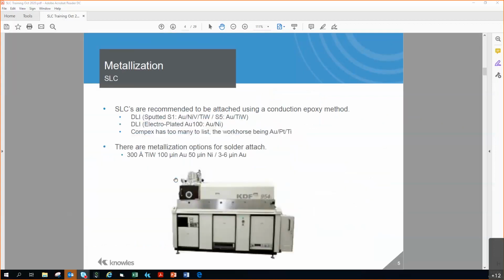All right. So a single layer capacitor is a single piece construction, but there is metallization on each side. We do 2 types of metallization. We use sputtering and we do wet plating. Typically, we have about 5 or 6, maybe even 7 now, different sputtering machines with 3 to 4 chambers in each sputtering machine.